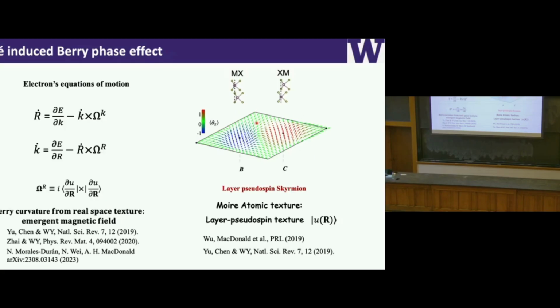Then imagine your electrons going through these pseudo spins in real space. You go through these skyrmions, so you must pick up this pseudo-magnetic phase. What it means is that now we have these layer pseudo spin textures giving rise to Berry curvature in real space, and that will give rise to these anomalous Hall velocities. So that's where this topology is coming from. And this becomes important because the topology is coming from these real space layer pseudo spin skyrmions.